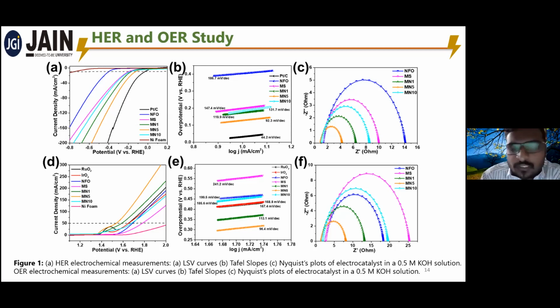The same kind of results appear in the oxygen evolution reaction study also, where we compared RuO2 and IrO2 with our synthesized catalyst, and their performance is even lower than our best catalyst, Mn5.